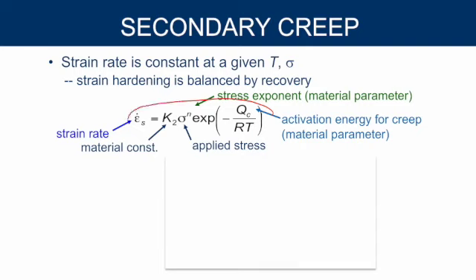So how does creep respond? Again, it uses the same equation we've used in the past, that if we increase the temperature of a material, its likelihood to creep or change length with constant stress increases exponentially. So we're using the exact same equation we've already used about 3 or 4 times in this class. This time it's the rate of strain, so deformation with respect to time. We have our K constant we've talked about. We have our stress, exponentially changes with the inverse negative of the temperature. So again, there's an activation energy for creep. Again, a number you would either experimentally find or look up in a table. And you have the exponential corresponding to temperature.